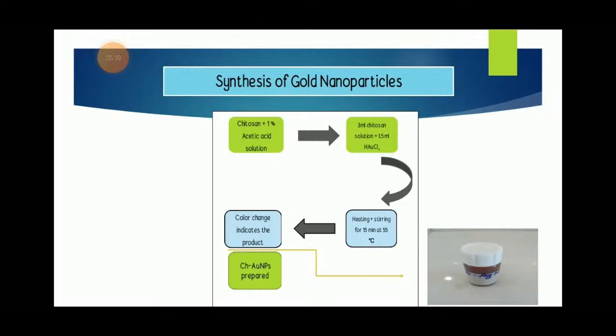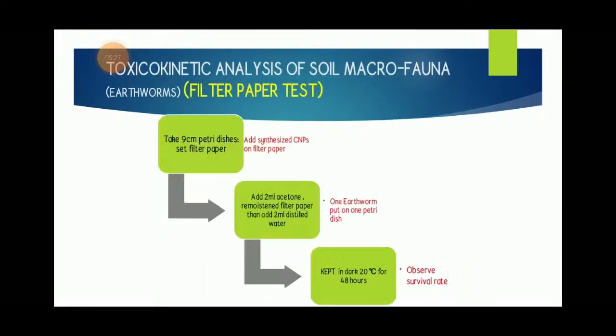And synthesis of gold nanoparticles: chitosan plus 1% acetic acid solution, 3 ml chitosan solution plus 1.5 ml gold solution, heating and stirring for 15 minutes at 55 degrees centigrade. Color change indicates the product. Toxicity analysis of soil microfauna earthworm. Filter paper test. Add synthesized CNPs on filter paper. Take 9 cm petri dishes, set filter paper. Add 2 ml acetone, re-moisturize filter paper, and add 2 ml distilled water. Put 1 earthworm in 1 petri dish, kept at 20 degrees centigrade for 48 hours.